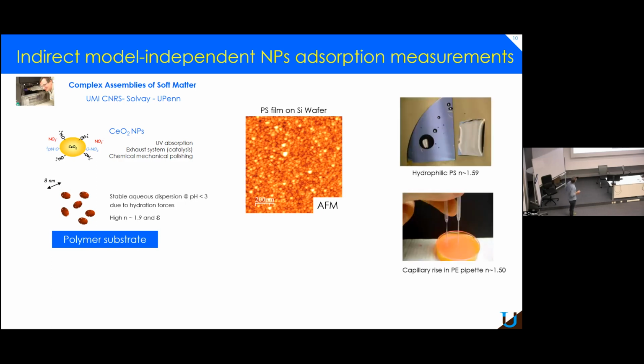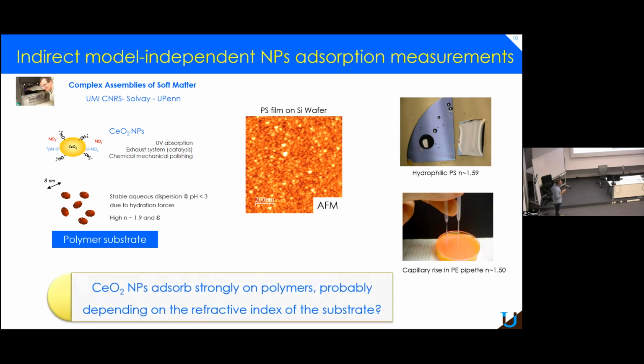This is a polystyrene thin film on the wafer, covered with nanoparticles easily. You dip it and the adsorption is quite great. This is the polystyrene layer without anything, and this is the polystyrene layer with this layer. So you can do it on pretty much any polymer. Here, for example, you have a pipette, the pipette that you use in your lab. If you cover it with a monolayer of particles, you can barely see the rise on a polyethylene pipette. So those particles were adsorbing on pretty much all polymers, even Teflon. We did the experiment. Obviously Teflon was not hydrophilic, but it was less hydrophilic. So we saw that maybe the adsorption was somehow governed by the refractive index of the polymer.